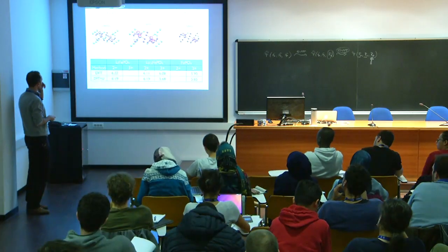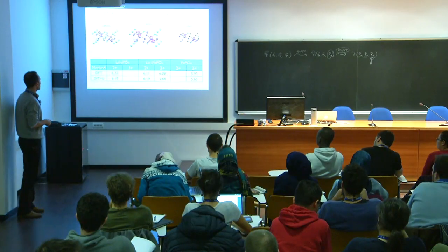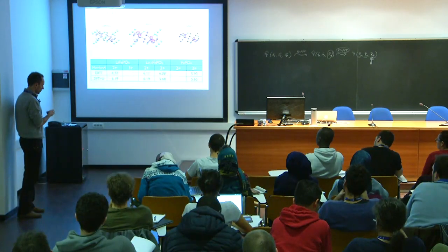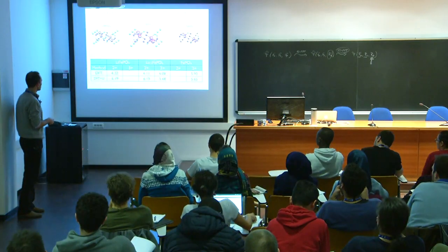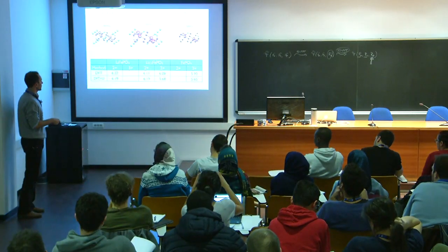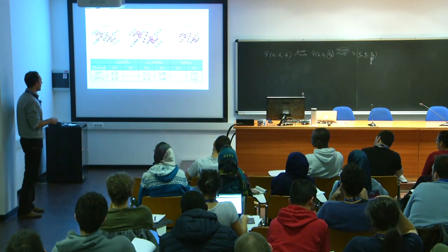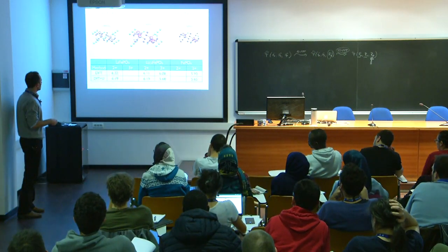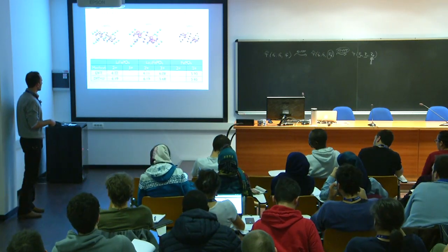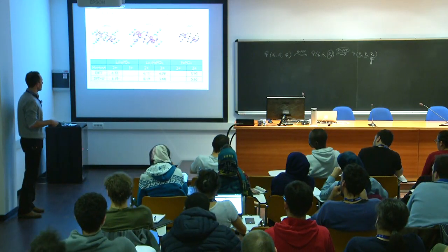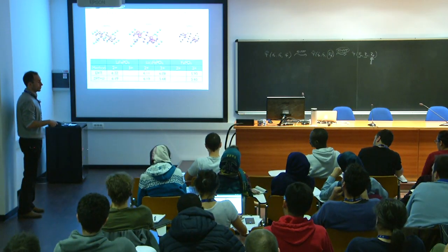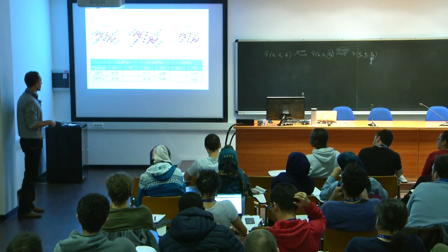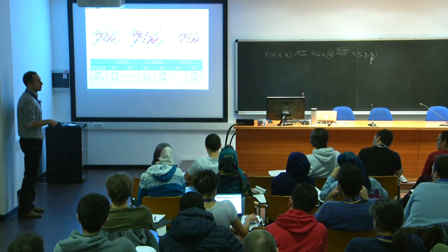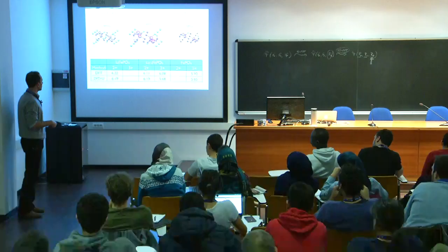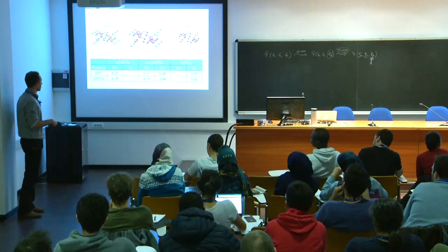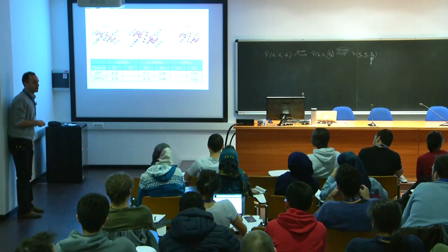So do we correct this case? So do we get a collection of 2 plus and 3 plus? Well, we get closer at least to that. We correct in the right direction. So you would expect, so this material with plenty of lithium has 2 plus iron, this other one has 3 plus iron. So when dealing with this, the half lithiated one, you want basically 2 plus being described like this, with the same amount of d electrons as this, and 3 plus the same amount of d electrons as this. And you see this is not true for standard DFT approximation. They're actually quite close to each other, so approximately 2.5 oxidation state, but you get closer when using this correction. So you get a 2 plus like a 2 plus and 3 plus very close to the 3 plus. So you manage to localize electrons.